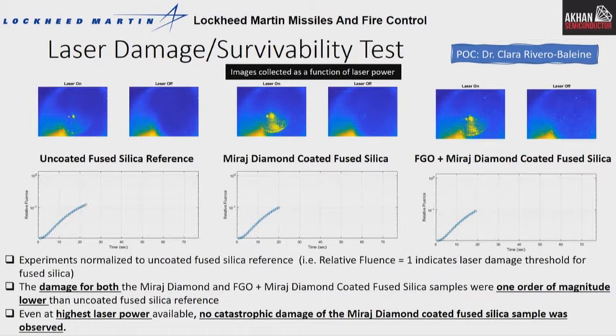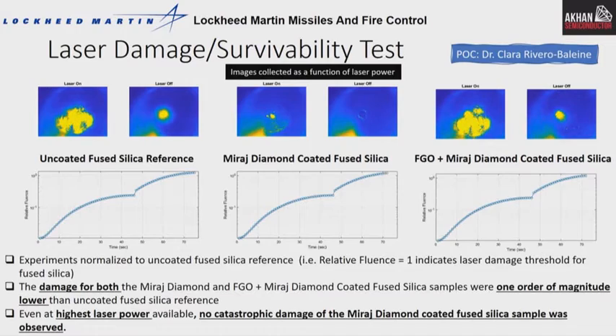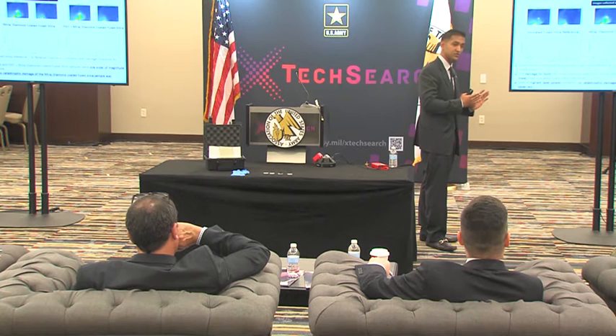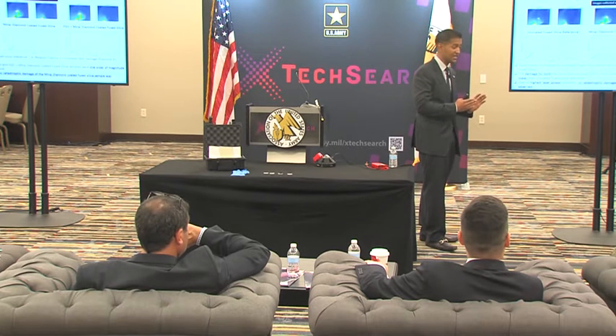And again, we see that the damage for both the Miraj Diamond and the Miraj Diamond FGO-coated sample was a full order of magnitude less than the fused silica reference. Most importantly, even at the highest laser power available, no catastrophic damage of the Miraj Diamond-coated fused silica sample or the FGO was observed. So we see that this material survives, proving the thesis that it is a durable construct against directed energy or laser weaponry. This can be tuned, I want to mention, to favor different wavelengths, so we can go to different laser modules. If we want to move to 0.8 or up, that's highly tunable.